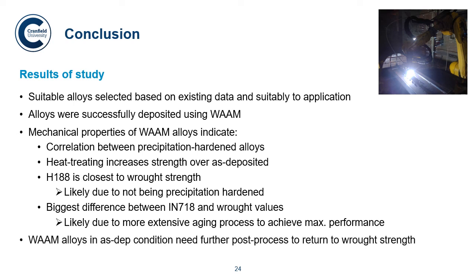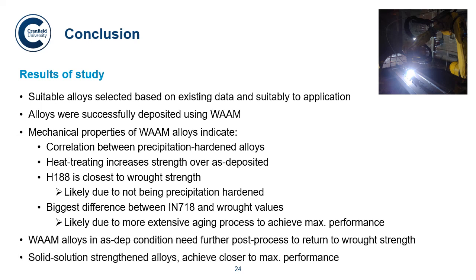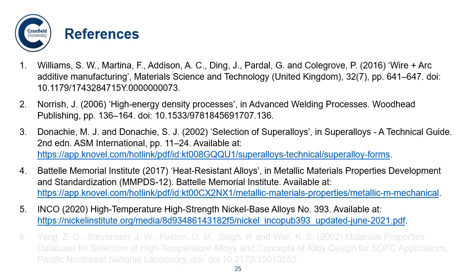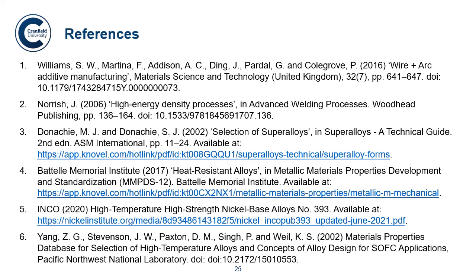And the WAAM alloys in as deposited condition clearly need further post-processing to return to wrought strength. So we're hoping to do another mechanical process after depositing, such as rolling or shot peening. And then solid solution strengthened alloys achieve closer to the maximum performance. That was just H188. And here are some references if anyone was interested in finding out more.